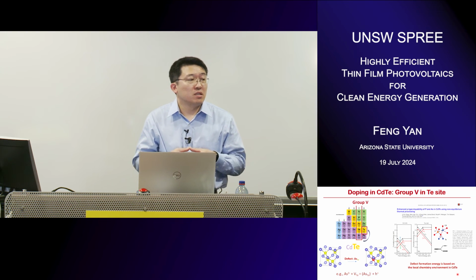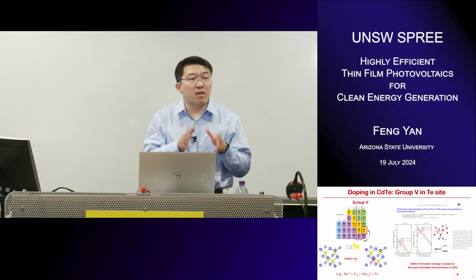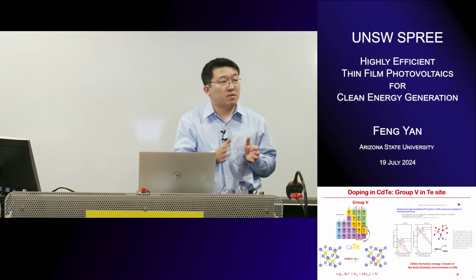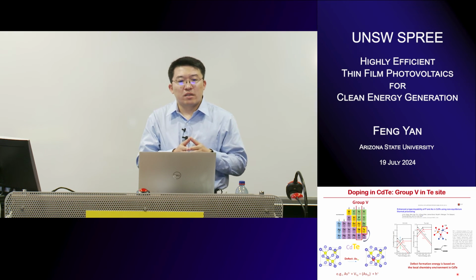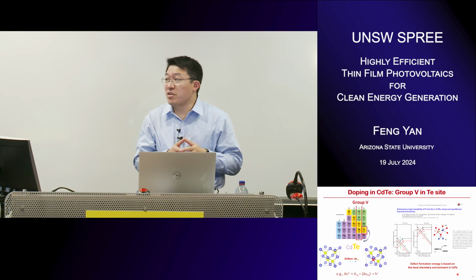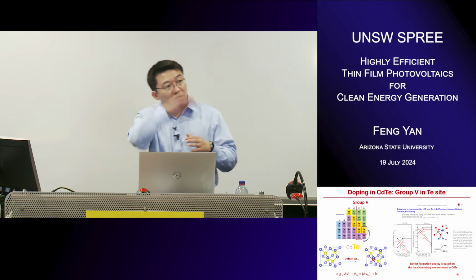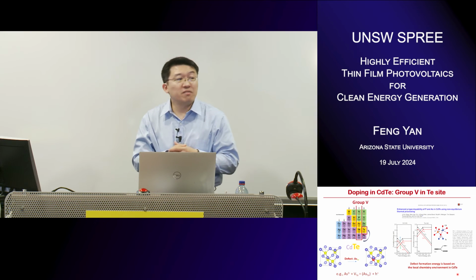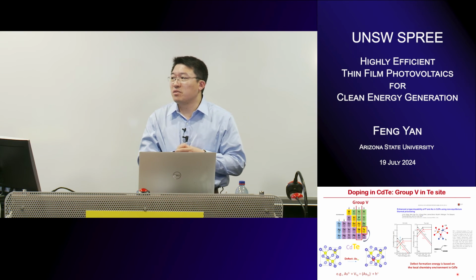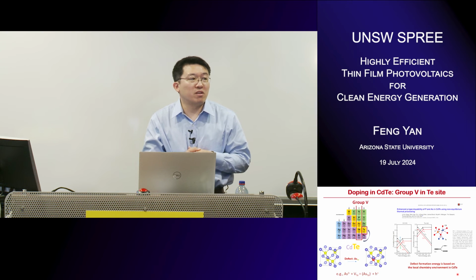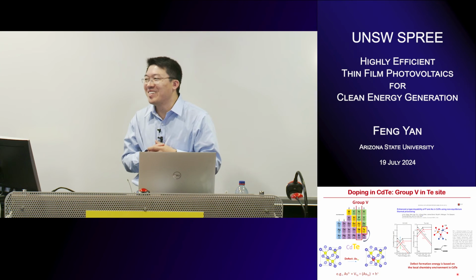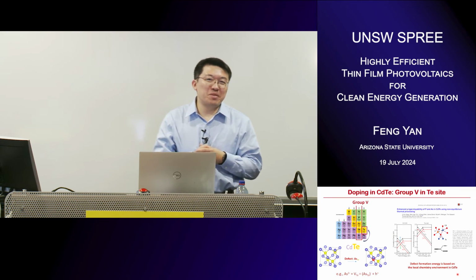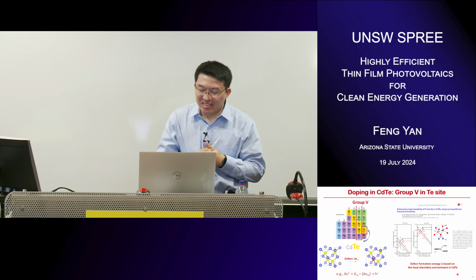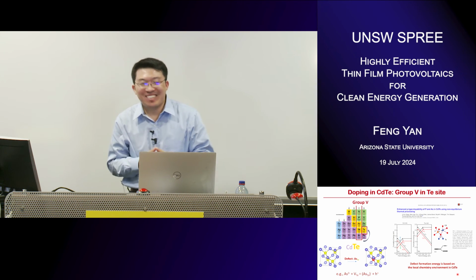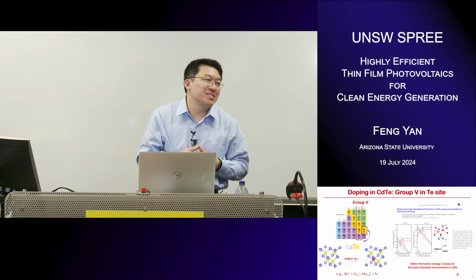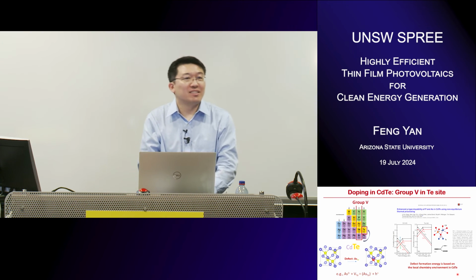So that's why the passivation is majorly finished after the cadmium chloride. That's why cadmium chloride treatment is pretty magic for CdTe. If you check the efficiency chart, it's significant, almost double. So it's a pretty amazing process. But it came from an accident, because some people probably threw some cadmium chloride in the processing line, so then they revisited the process to get it. Thank you.